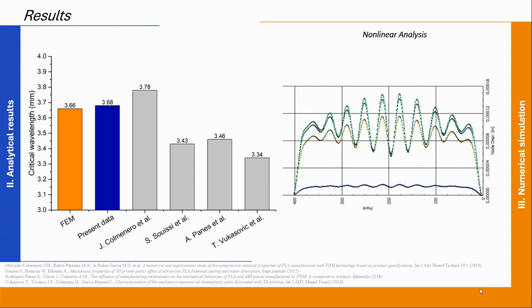We perform a nonlinear analysis to investigate the displacement increment trend. To trigger the distortion, we used an initial imperfection similar to the wrinkles distortion that we observed in the buckling analysis, reduced so that the maximum displacement was equal to 1/10 of the skin thickness. The outcome of this analysis highlights how the load-displacement relationship is nonlinear. In the picture, the development of the wrinkles is shown at each increment.